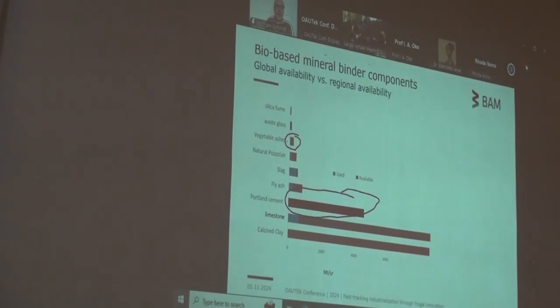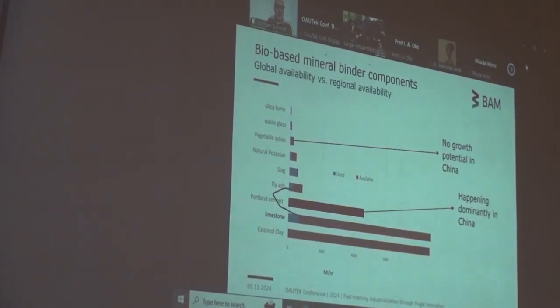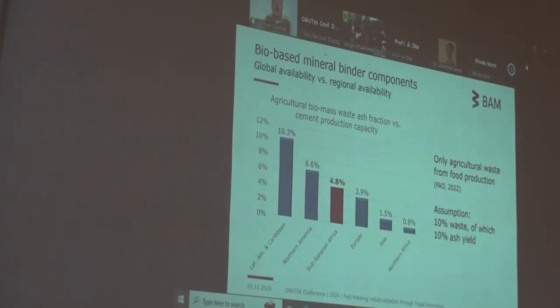But first of all, the order of magnitude of the vegetable ashes is comparable to natural pozzolana, to slag, and to fly ash. So I would not say it's a negligible amount, but then we also have to see that the overall Portland cement production number is dominated by China. But China has to import food, so there's no growth potential in agricultural products, which means the vegetable ashes are not growing in China. If we convert the same figure and look at it in different parts of the world more regionally, we would identify that in